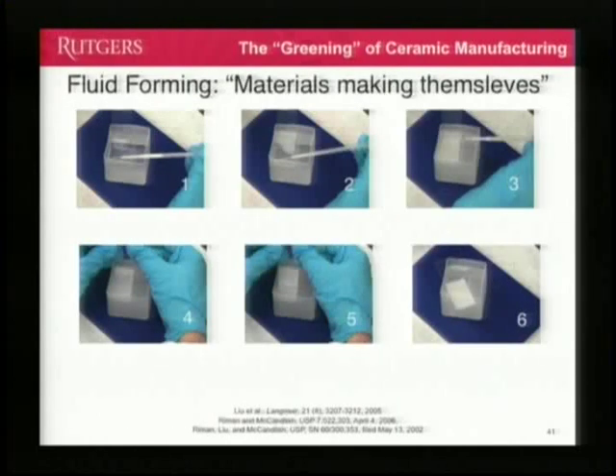And so here's another one, just as a last example. We have a bunch of particles. Maybe we made them at low temperature. Instead of using high pressure, high energy equipment to assemble things, let's use self-assembly. So what we do is we take the particles, they're suspended in a liquid, we drop them onto a water bath, and we functionalize the surface so that the particles float on water. So here we're floating something that's 8 grams per cc on something that's 1 gram per cc. We make it so non-wetting it can support its weight.